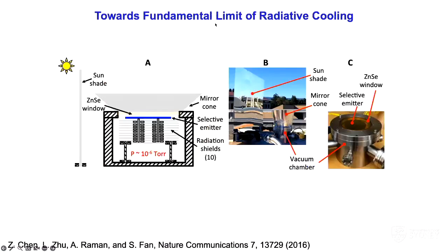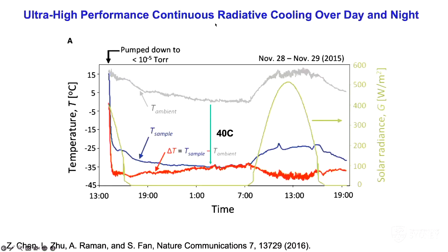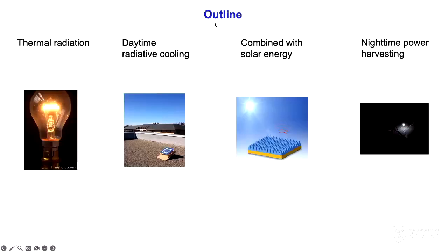Then Dr. Zhen Chen, my postdoc at the time, who is now a professor at Southeast University in China, carried out this experiment. He took the radiative cooler and put it into a vacuum chamber to cut down parasitic loss. The vacuum chamber has a zinc selenide window so that the thermal radiation can still get out. And he saw that you can indeed get a temperature that is 40 degrees Celsius below the ambient air temperature during both daytime and nighttime. In other words, one really can get sub-ambient, sub-freezing temperature over 24 hours with this kind of radiative cooling idea, if you build sufficient insulation around the radiative cooler. So I guess that gave you perhaps some sense of what one can do with controlling thermal radiation.